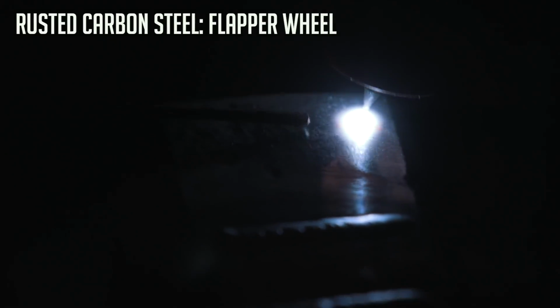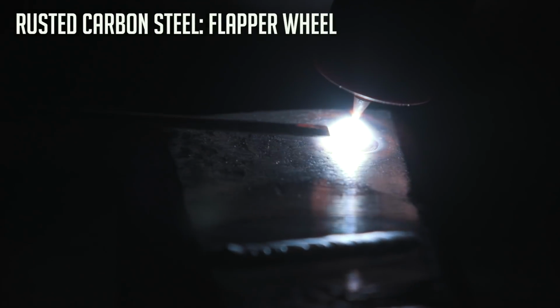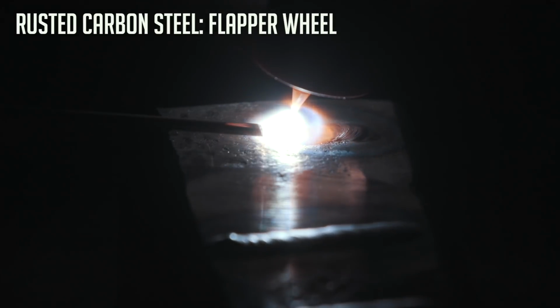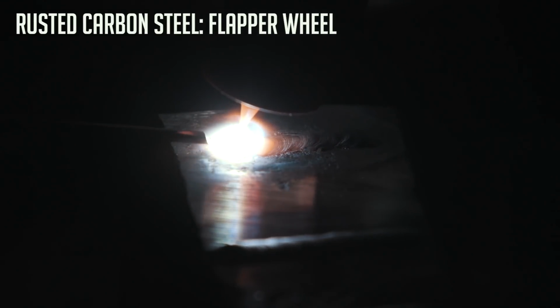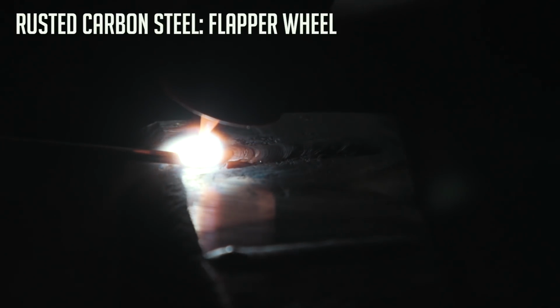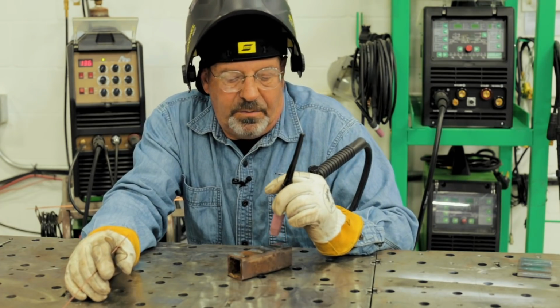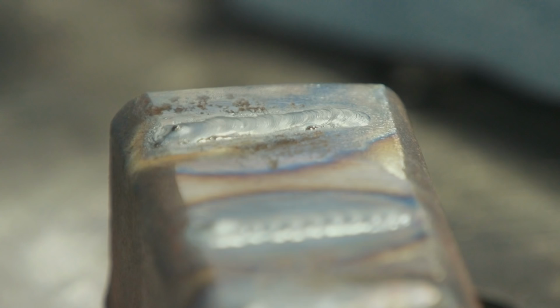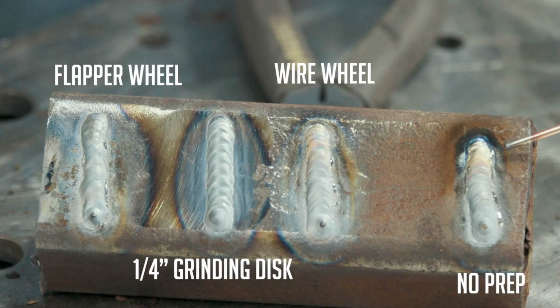And then the last one is where we cut with the flapper disc. Again, it got into the leading edge the way it was laid on there, but as I came across, it just kind of sat up on top of this over here. It buffed the top of it off, and that was about it. And we're back to the weird reaction of the stuff in the weld pool and on the edges. A little pond scum going on and some reaction. So by far, the one that welded the best on this particular part was the one that was cut with the disc right down to clean metal.